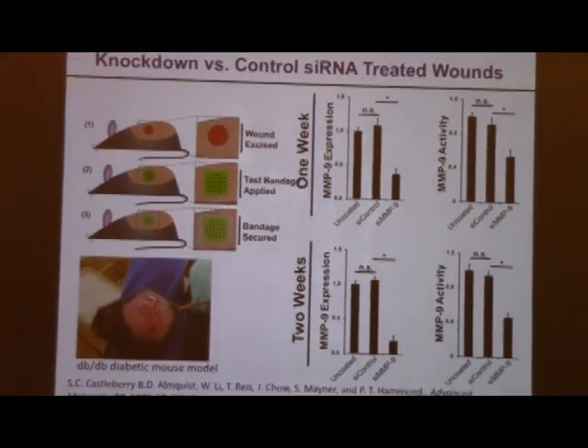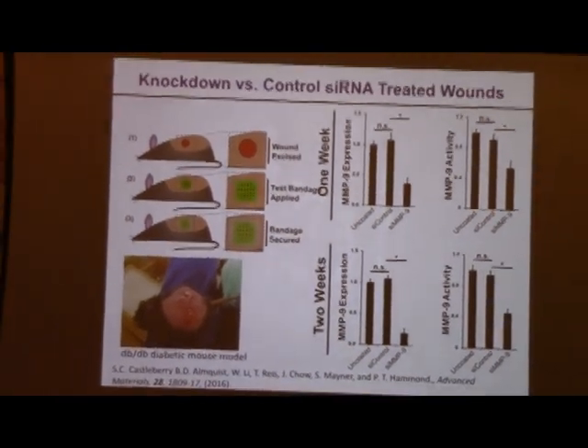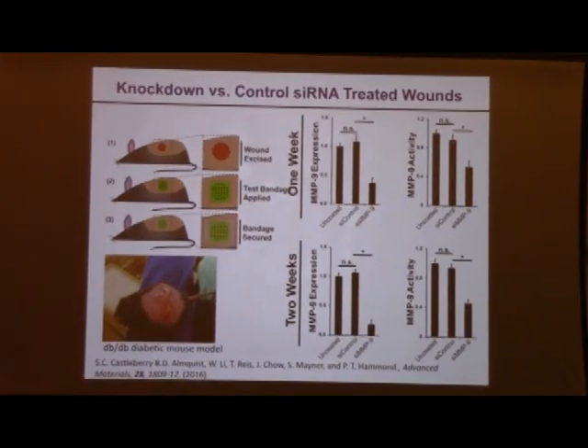We optimized those layers using in vitro tests and cell culture, and then we used a diabetic mouse model to test them. In this case, these are mice that intrinsically are diabetic. They're not induced. And for that reason, we can introduce two wounds on the backs of the mice and look at the relative rates of wound closure. So we looked at untreated wounds, wounds treated with the siRNA against MMP9, and wounds that contained siRNA that didn't encode for anything as a control.